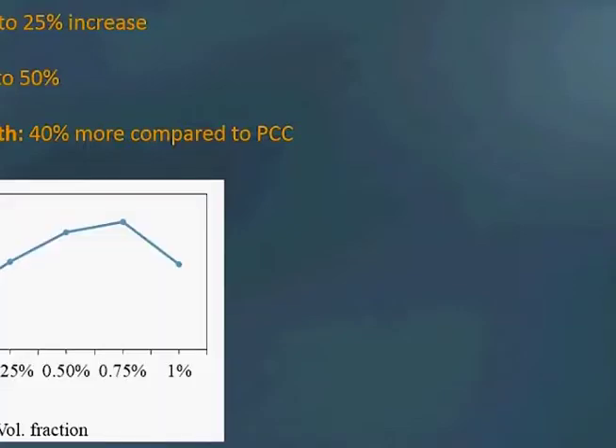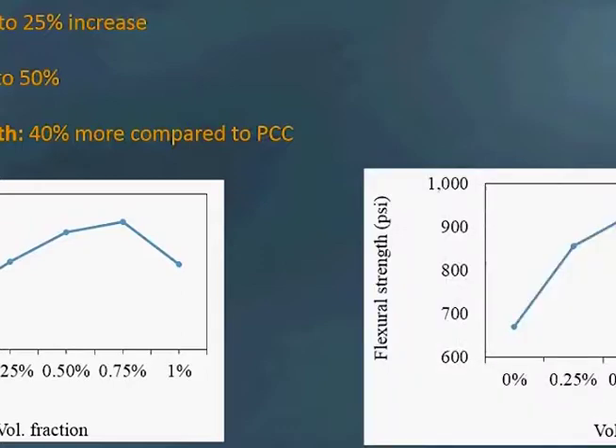In steel fibers, even though they were not used in too many states, a few examples are there in Illinois. Steel fibers sometimes help in increasing the compressive strength. You can see here the compressive strength increases, but if you have too much, eventually it doesn't, because of the concrete's compressive strength, and only a few particular fibers are in the vertical or horizontal directions; a lot depends on the orientation too. Sometimes we screw up if we pour too many fibers. Flexural strength can also be increased if we add steel fibers. People say 50%. There is one study here that I referred to, where they said they can increase it by 50%.